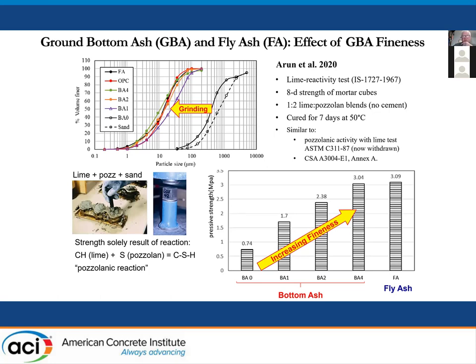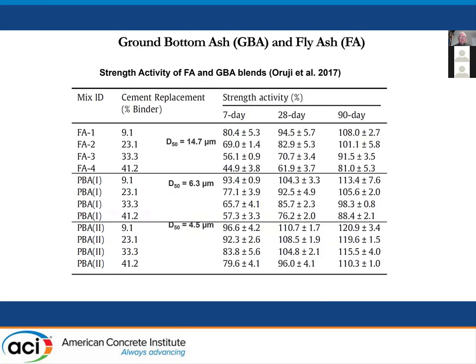But in a number of papers, if you take raw bottom ash, shown in the particle size on the right, and you grind it down to the same particle size as fly ash, and you make 50 millimeter, 2-inch cubes, you can get really good compressive strengths. So you can see the compressive strength coming up with the bottom ash. The bottom ashes are shown in red, the first four bars, compared to the fly ash. If you grind the bottom ash enough, you can get the same compressive strength as the fly ash from the same source.